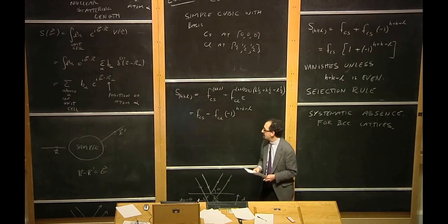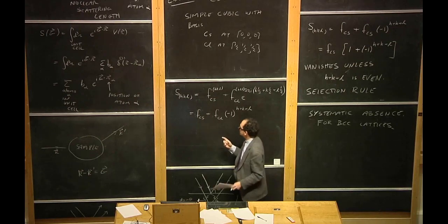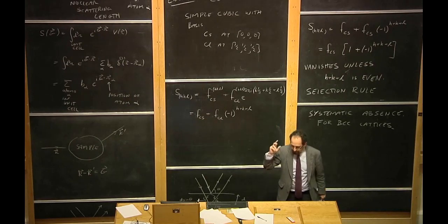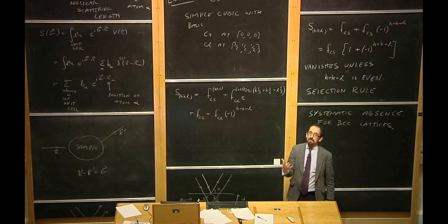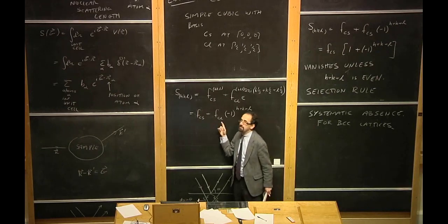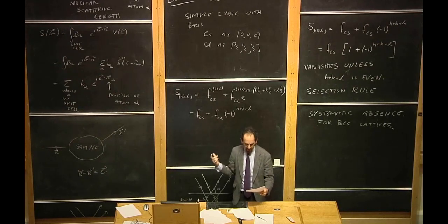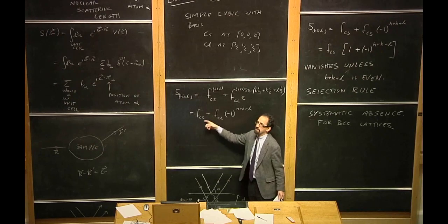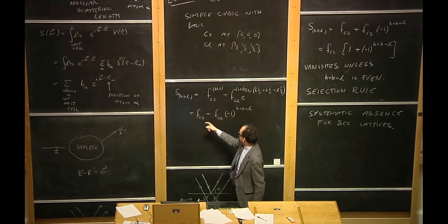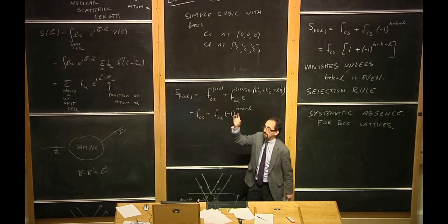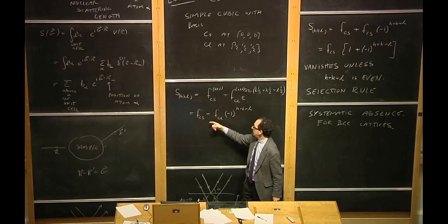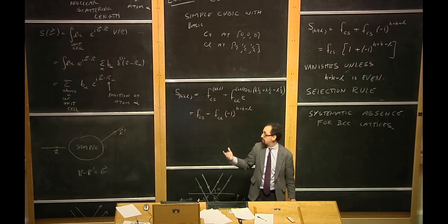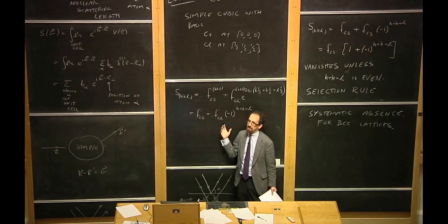Potassium chloride is a very good guess, and the reason is that these form factors are basically proportional to the atomic number. And the atomic numbers of cesium and chlorine are extremely different. Chlorine is number 17, and cesium is number 55. So these two numbers will be extremely different. But if you replaced the cesium with potassium, which is right above it on the periodic table and chemically very similar, then potassium has atomic number 19 and chlorine has atomic number 17. So these would be pretty close to each other, and you'd have a near cancellation.